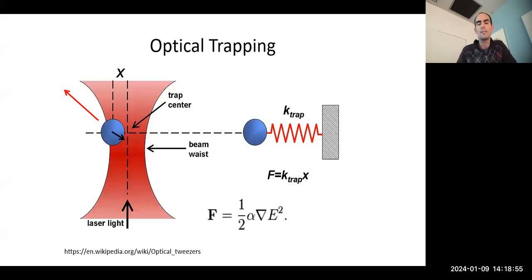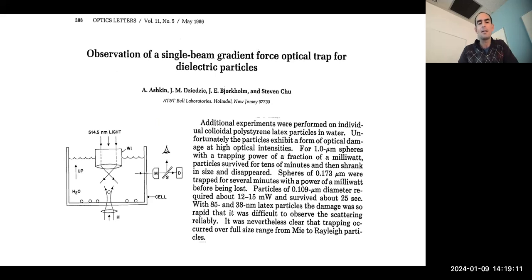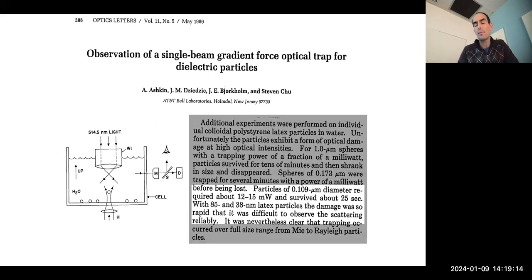In doing so, you can hold on to that particle and learn about it. The force on the particle is proportional to its polarizability, which means that as you make your particle smaller, the force gets smaller to the third power of the size of the particle. So that's not great — you can easily trap particles about 100 nanometers or larger, up to a micron. But below 100 nanometers, Arthur Ashkin realized you end up destroying your particles, or you can't hold onto them long enough.